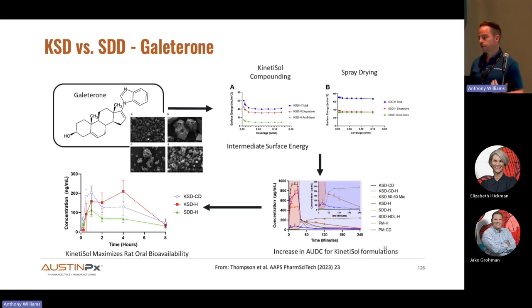But for a majority of compounds that we see, the crystallization kinetics, precipitation kinetics are quite rapid, and polymer protection of the amorphous payload is key. And so I think this is a real effect for most compounds, that KinetiSol would outperform spray drying.